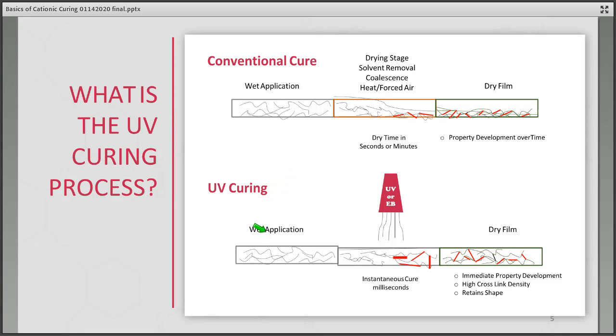In UV curing, you have your wet application, very similar to conventional cure. It's then exposed with UV or EB light. You get pretty much instantaneous cure in milliseconds for free radical now. And you end up with your dry film just about retaining the same thickness. You get immediate property development, a very good cross-linking density, and you tend to retain the shape.